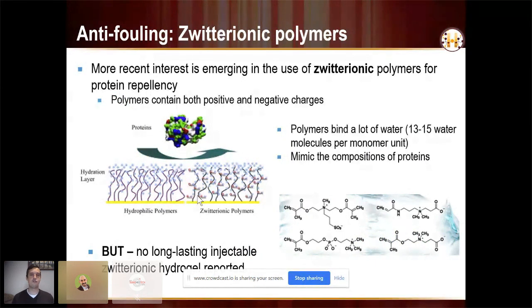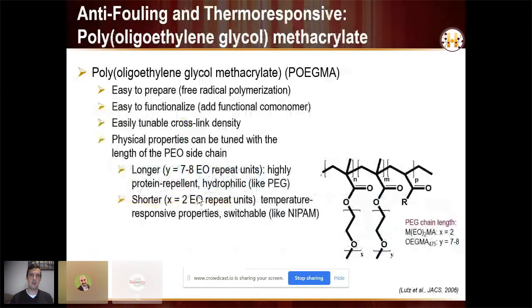But when we started this project, at least, there was no injectable hydrogel based on a zwitterionic polymer that would last any period of time. There was one reported, and it was a very short-lived polymer. So in terms of addressing some of these challenges, zwitterionic polymers we can use directly. There's no concern with actually translating these in the body. But as a substitute for PEG, which has these cross-linking challenges, and polyNIPAM, which has these toxicity challenges, we really focused on this polymer called oligoethylene glycol methacrylate, or PEGMA.